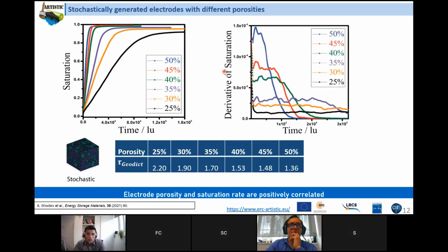Now in our model, we can also look at the rate of the electrolyte within the structure, the average rate. As you can see here, this represents the rate, by time step, as it goes through the structure. The higher the porosity, the higher the rate or velocity of the fluid within the structure, and it goes down because, of course, it's finished, right? And the structure reaches 100% here, so that's why velocity goes down, all of them almost. And then accordingly, it goes straight forward this way.